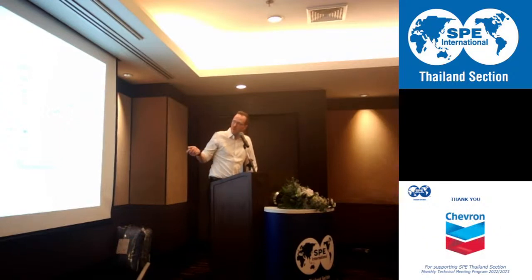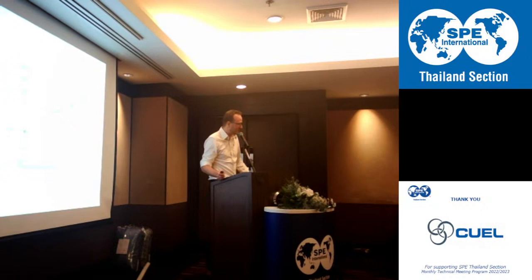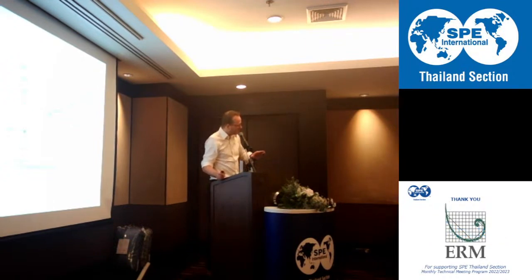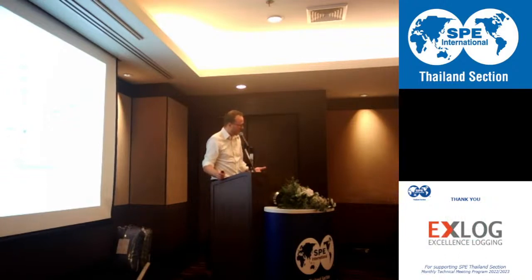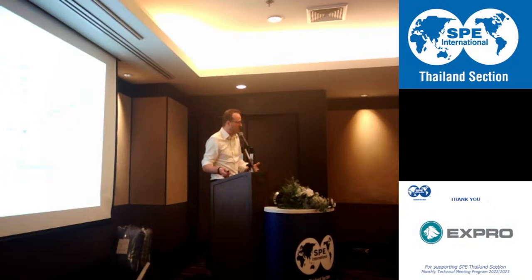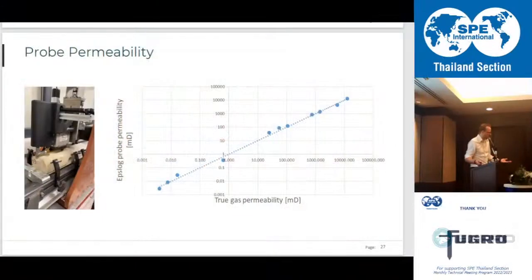And you could argue that those data are fake because they seem to be very, very good. But again, because we prepare these surveys at the micron scale, you start to have some very good sealing properties. Of course, if you have extremely large grain size, that can start to leak, but that will be the problem, let's say, of any kind of permeability test. But basically, we go from less than a hundredth of a millidarcy to more than 10,000 millidarcy, to 10 darcies.